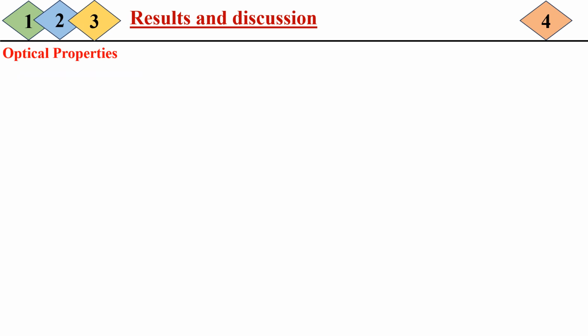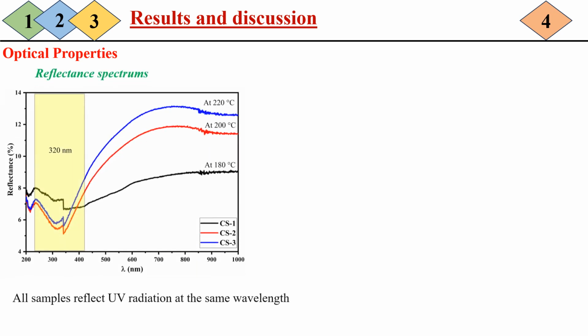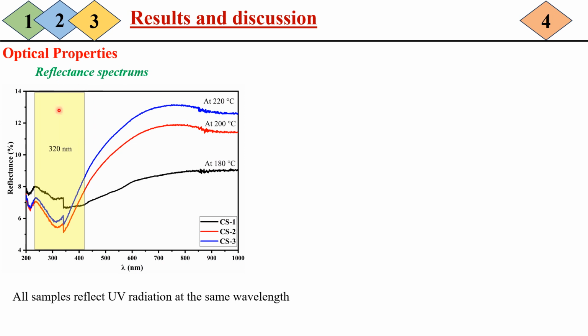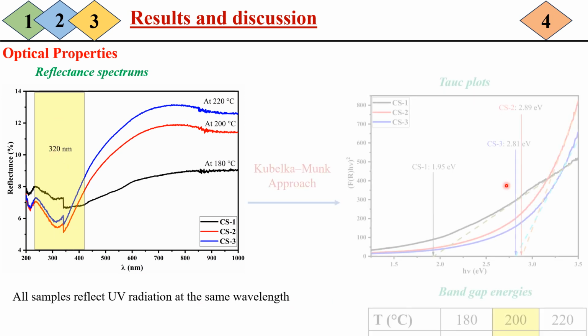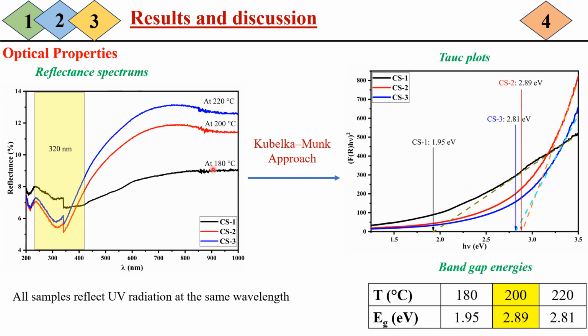To determine their band gap energies, our samples were characterized using diffuse reflectance. As we can see, all samples reflect UV radiation at the same wavelength. These spectra have been processed using the Kubelka-Munk function to determine the band gap energies of each sample. As you can see from the top plot, sample number 2 has the highest band gap energy, which is about 2.89 electron volts.